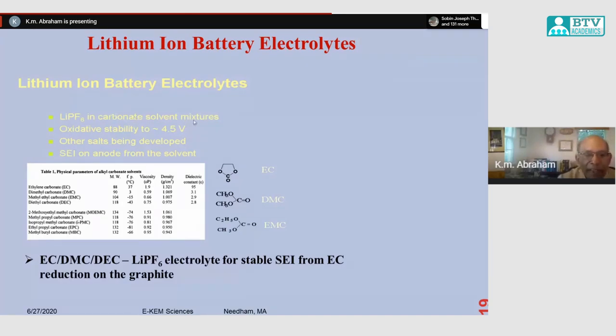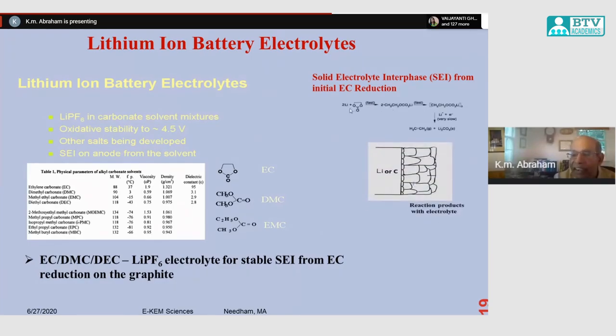So ethylene carbonate is a very important electrolyte. This is the ethylene carbonate, dimethyl carbonate, ethyl methyl carbonate. In a practical battery, a mixture of two or three of these carbonate solvents is used to make the electrolyte for a lithium-ion battery. Ethylene carbonate is a solid at room temperature, because it has a melting point of 37 degrees centigrade. However, it's a very important solvent for lithium ion, because it is the solvent that forms the solid electrolyte interface that we talked about earlier. That happens from the reduction of the EC.